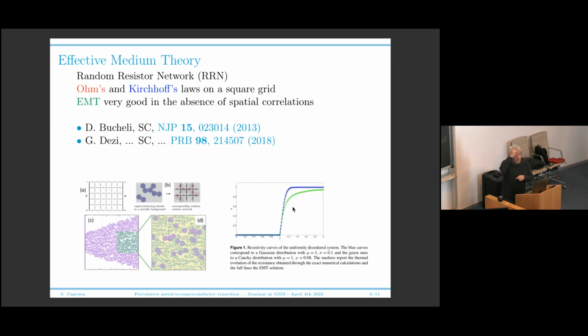In both cases, you exactly reproduce the exact numerical solution of the random resistor network with your effective medium approximation. Now, we wanted to go beyond effective medium. But as you see, effective medium gives a very good description of the solution if disorder is really random. So our next challenge was, imagine that for some reasons, which maybe you don't know, your superconducting cluster is not really random. Maybe for some reasons, this is a rather filamentary object.